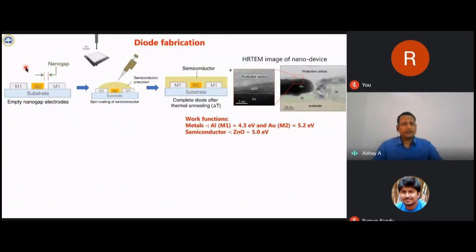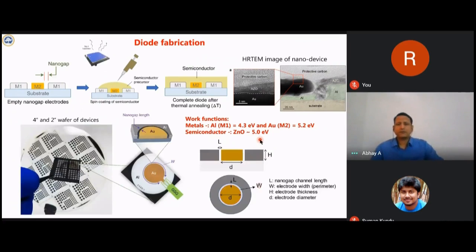In the next step, we take that chip which has gap electrodes and spin coat our semiconductor on top of it, using an ink of zinc oxide, and then we heat it at some temperature to evaporate the solvent. This high resolution TEM image shows the aluminum electrode and gold electrode, and the zinc oxide material filling that nano channel. Note that aluminum has a work function of 4.3 electron volts and gold 5.2 electron volts, while semiconducting zinc oxide has a work function of 5 electron volts. These are the chips which we fabricated on 2-inch and 4-inch wafers with hundreds and thousands of devices on them.